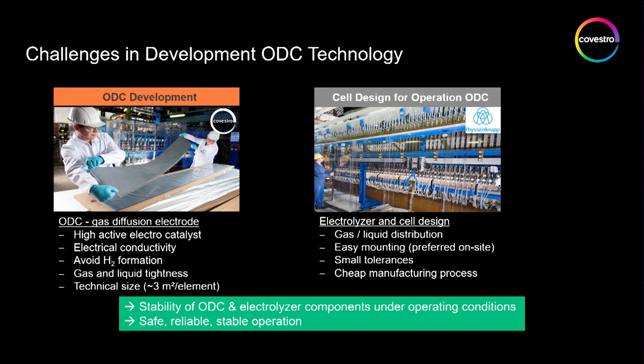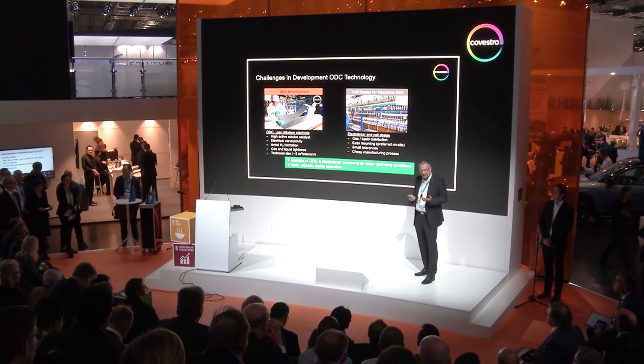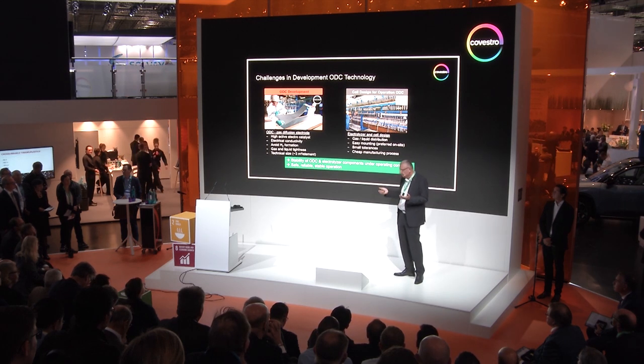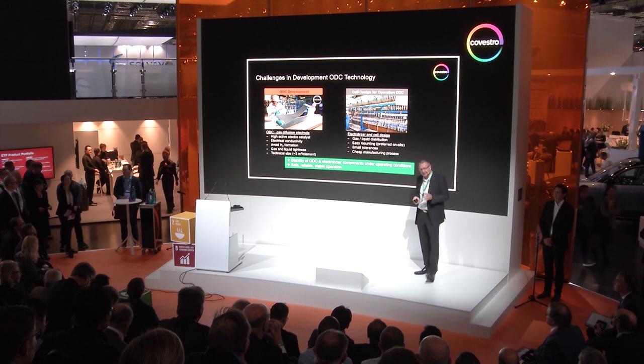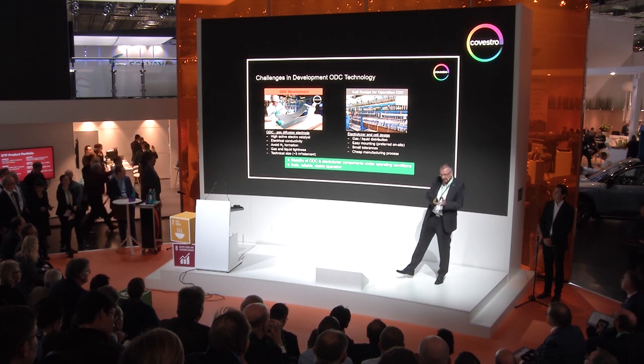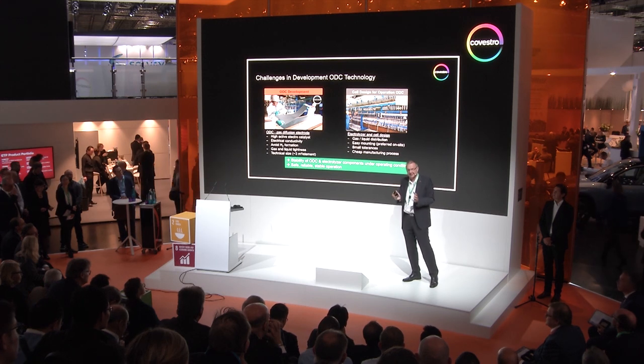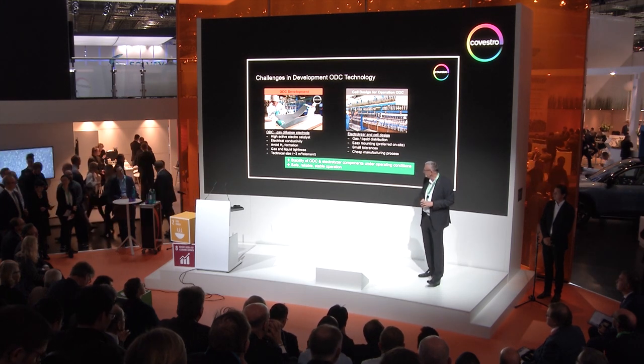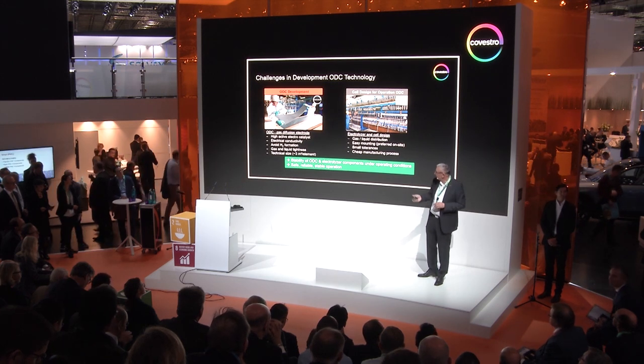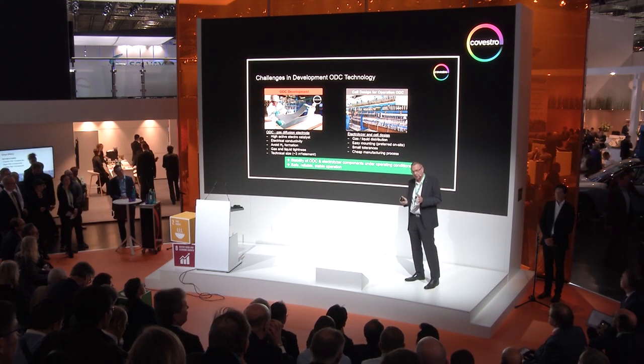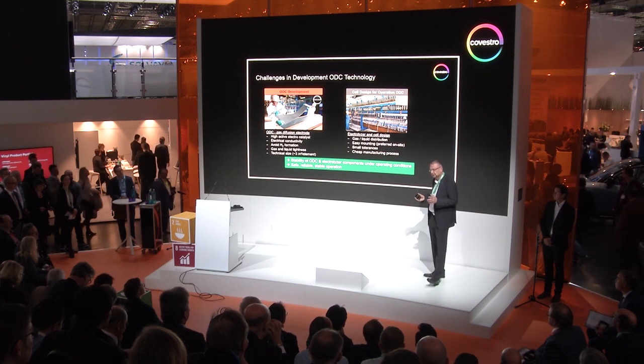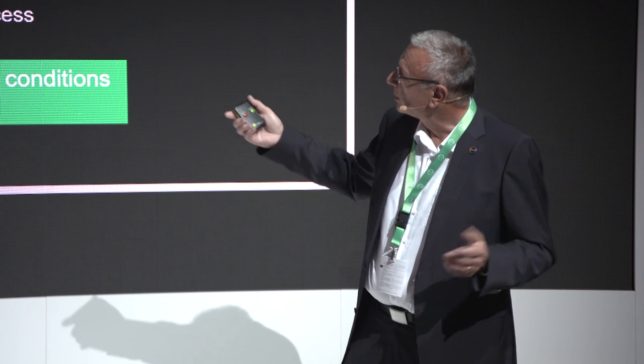So the main challenges for the ODC were that we need a highly active, electrically conductive electrocatalyst. Then the gas and liquid tightness is important, and the technical size is very important. If you come from the fuel cell, they are working in 10 by 10 square centimeters, but we have to employ gas diffusion electrodes, oxygen depolarized cathodes, in square meter ranges, because we're talking about basic chemicals which have a scale of 100,000 tons and more. For the electrolyzer, of course, the gas and liquid distribution is needed to employ the ODC, and small tolerances to keep the energy consumption low.